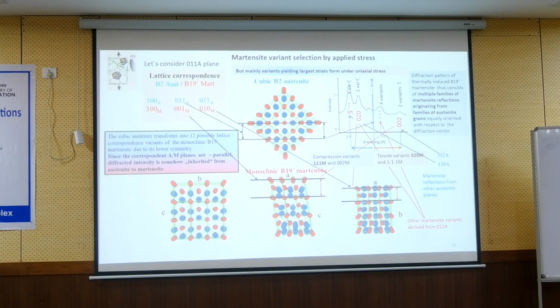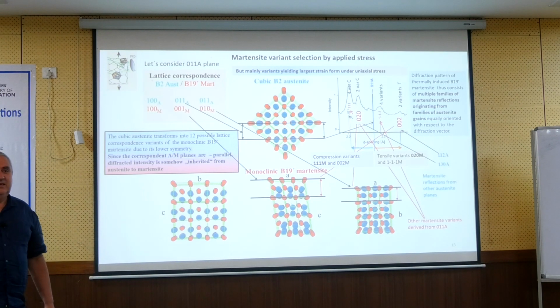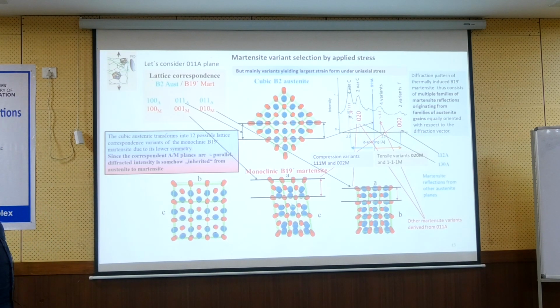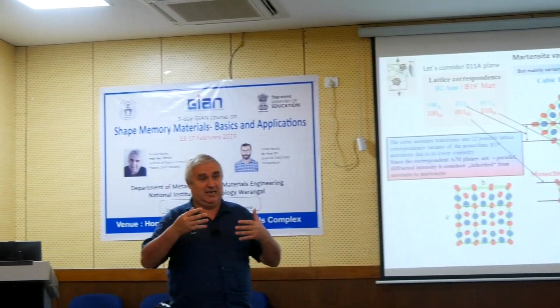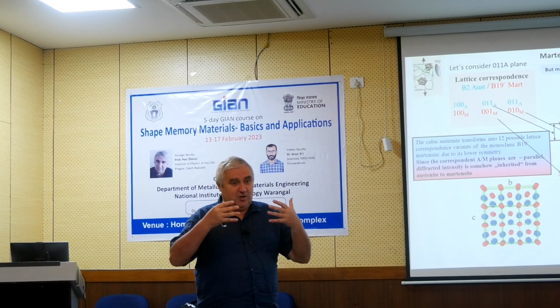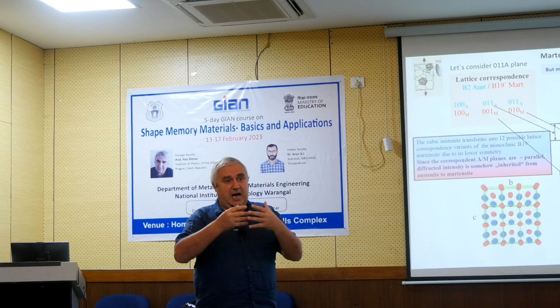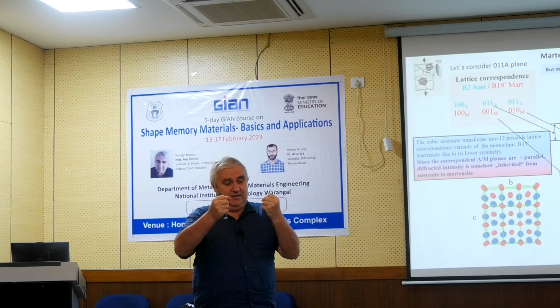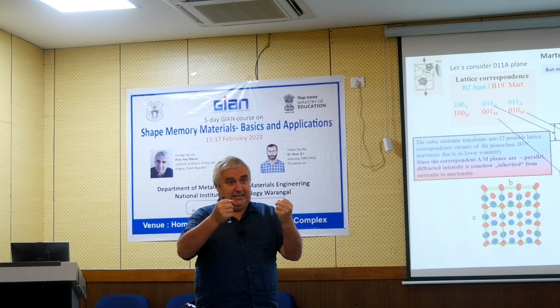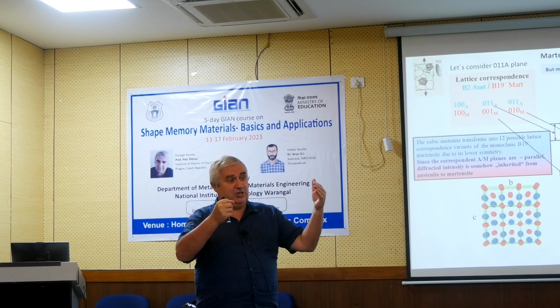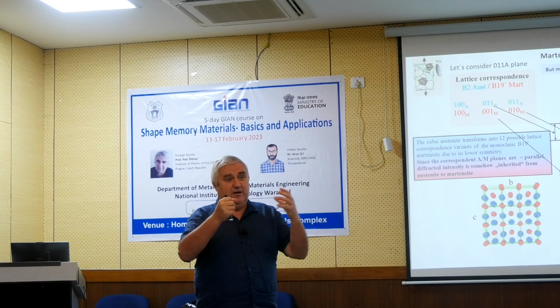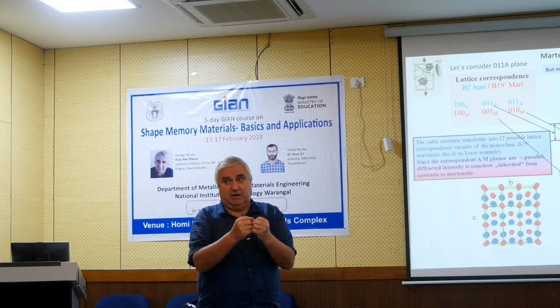So here, lattice correspondence. Here we are talking about which martensite variant, B19. I will be talking about lattice correspondence after that. I know it could be a little bit puzzling for you, but in any martensitic transformation, the lattice correspondence is the basic. In steels, they have this Kurdyumov-Sachs relationship derived, but this all reduces to lattice correspondence, which means how the austenite is rotated with respect to the martensite lattice. Depending on the type of the transition, you might have 6 or 12 or 4 different variants, but the lattice correspondence is a single one.